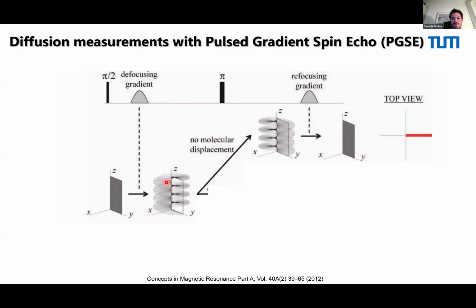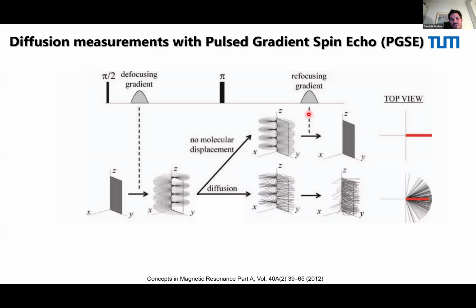What will happen is these spins, as I told you, will be rephased by this magnetic field gradient. You add your minus sign of the pi pulse here. And what we know from our spin echo is that it will rephase, and with the second gradient we get our spin echo, where these induced gradients will disappear. So what happens now if we have diffusion? And now that's exactly what we want to go into. If these spins change their location, so they diffuse along this gradient, you will not be able to refocus all of the spins, and this will lead to a reduced signal in the spin echo. And this we can use to perform very precise measurements of diffusion with magnetic resonance.